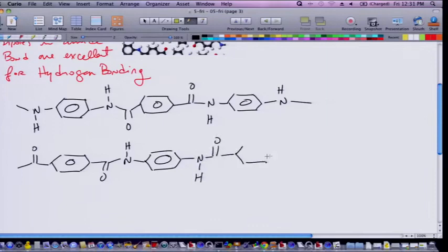So, this is kind of a redundant exercise, but you should be able to do this. And you can see when you do this exercise that everything, if I were really religious about this, I would have made all my bond lengths perfect distances and so forth. And you would have seen that the hydrogen bonding donors and acceptors line up perfectly. And that's because of the regular pattern of this. Also, the other thing that really is conducive for good hydrogen bonding in this polymer is that it's para-substituted. And that makes these polymer chains rigid and long. And then when they orient their groups towards one another, they're in a rigid line. And that makes for a perfect alignment of these hydrogen bonds. You're not fighting the floppiness that you can see in other polymers where the chains want to reorient. So anyway, the bottom line is this: you get a massive network of hydrogen bonds.